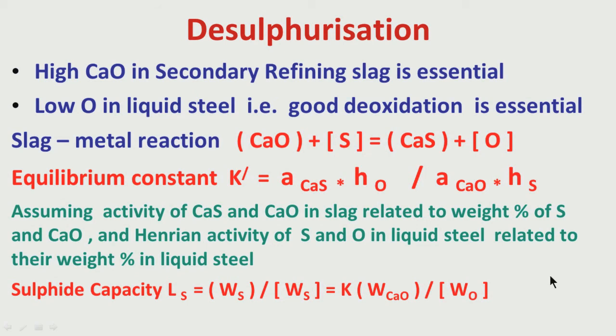Now, is it clear why every time I have been talking about deoxidation having to be done first? If deoxidation is done, the oxygen level in steel comes down. This helps not only in creating a low amount of total oxygen, but also helps subsequently in desulfurization. So, high CaO in secondary refining is essential. Also, low oxygen in liquid steel, that is good deoxidation, is also essential. So, there are two requirements for good desulfurization. First is a good amount of CaO, more than 50%. The basicity, meaning CaO by SiO2 ratio in slag, has to be more than 3.5 is better. And another important requirement is that the oxygen in liquid steel has to be low. That means good deoxidation prior to desulphurization is essential.